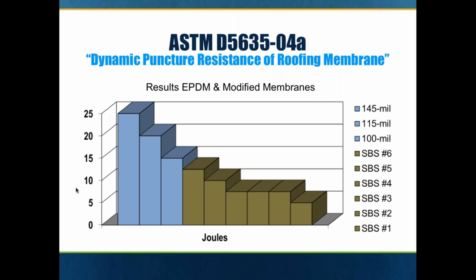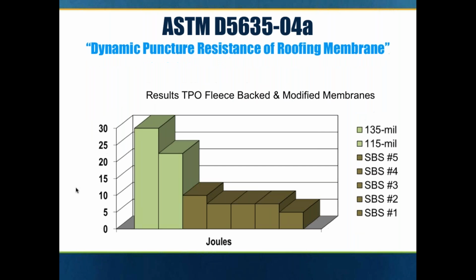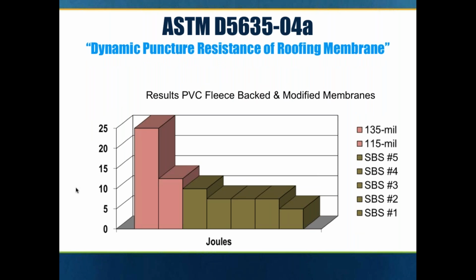And the attributes for puncture resistance are pretty impressive. So the dynamic puncture resistance, according to ASTM D5635, compares EPDM in various thicknesses to a number of different SBS 2-ply modified systems. In this test, you generally drop a blunt object onto the membrane and see if it ruptures the membrane. So there are testing results for EPDM in this type of test, as well as TPO and PVC. And all three of the membrane categories exceeded the puncture resistance of a 2-ply SBS modified system.